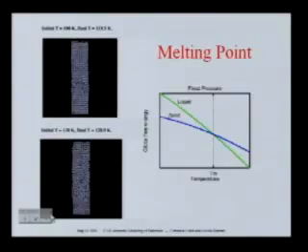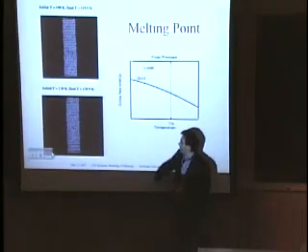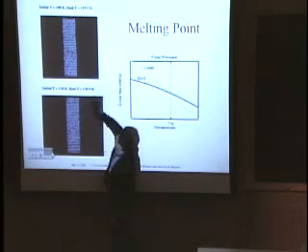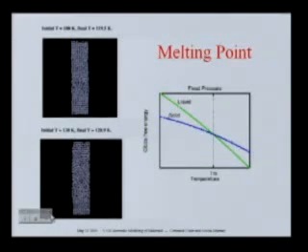So once you believe iron, now the issue is trying to figure out what is its phase diagram, at which temperature you have coexistence between the solid and the liquid. And you have actually done this in your laboratory 4, an explicit method to find out the transition temperature by doing a simulation of a liquid and a solid phase and figuring out at which temperature the boundary between the two phases doesn't grow into each other. So the solid doesn't keep growing or the liquid doesn't keep growing. And you'll see an example of this in what follows.